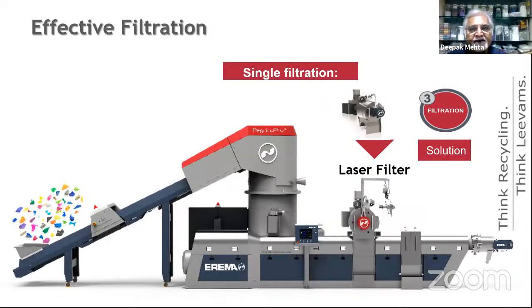Equally important is the filtration. Post-consumer waste does have a lot of leftover contamination. Despite the best of washing that you undertake, it still has embedded sand particles or embedded particles within the film structure itself. So effective filtration plays a very important role. Normally for post-consumer waste, the observation reveals that leftover contamination is more than 2%, 3%, going up to 5%. And this is where the laser filter plays a very important role in removing the leftover contaminations.